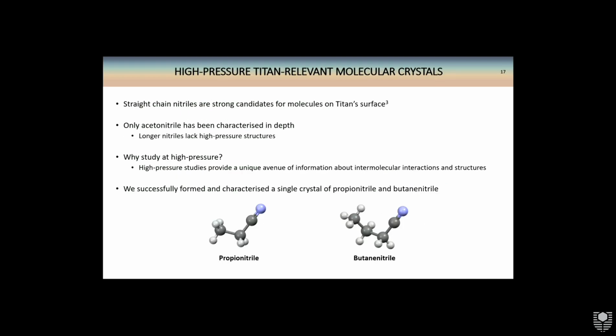So straight chain nitriles are strong candidates for molecules on Titan's surface. The lower chain ones have actually been detected and are known to exist, and the longer chain ones have been predicted to exist in relatively large quantities. However, only acetonitrile has actually been characterized in depth. Every other longer chain nitrile doesn't have a high pressure structure, and if you go not even too much higher, you don't see any structures at all.